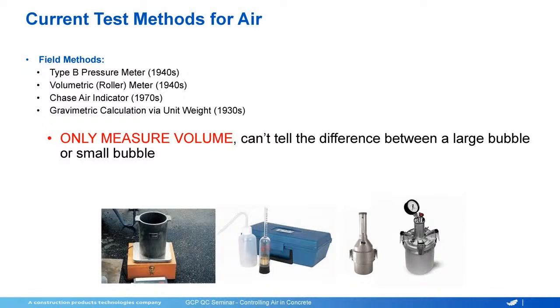Test for air entrainment. Now, I'm going to get on a hobby horse here for a bit. The chase indicator is not a test. However, if you are having difficulty having consistent air entrainment, it is a good tool to use to do a quick test on each batch that you make. Very simple test to run. It will give you an indication of what the air is. Obviously, you're only testing the mortar in this test. So it's not going to give you as accurate of a reading as the rollometer or the pressure meter, but it is a really good test to run.